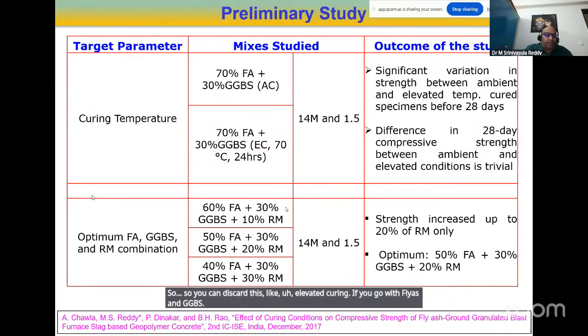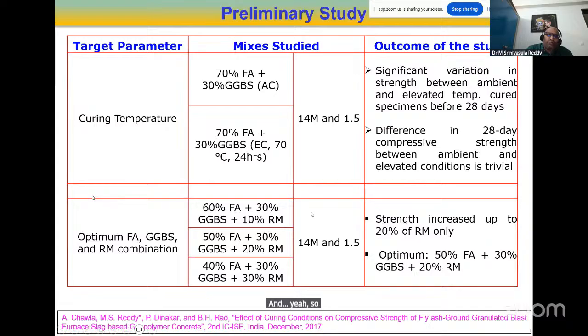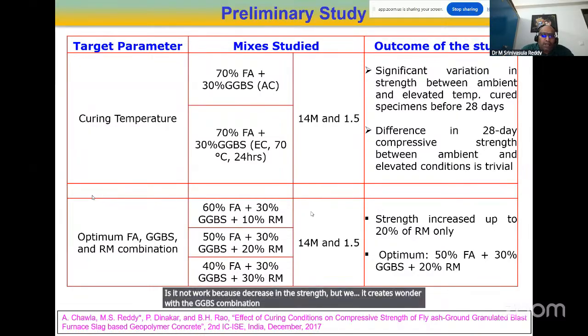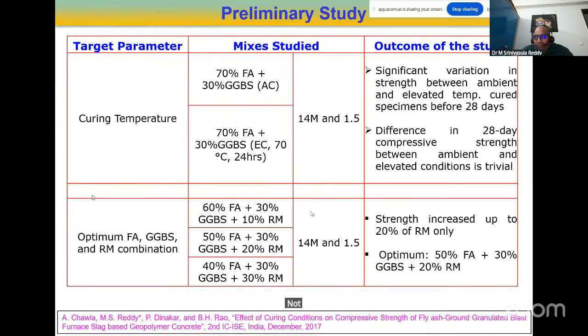And yeah, the red mud with the fly ash did not work because I observed a decrease in the strength. But it creates wonders with the fly ash and GGBS combination, not by participating in the reaction, but by filling the pores, because these red mud particles are finer than the GGBS.